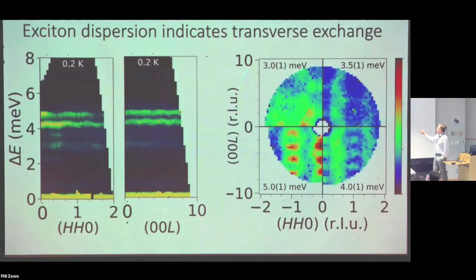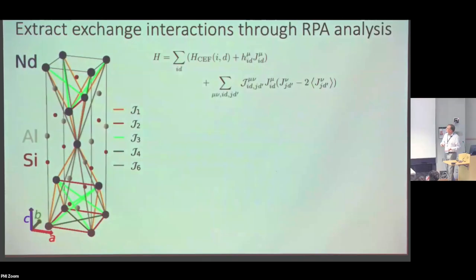This is another way of showing the same data, actually, which is just a slice through these same data at 3 millielectron volts, and you can see these things sort of coming into view and leaving view at different energies. So this is 3, 3.5, 4, and 5, sort of moving in this region, we get these interesting structures. So there's quite a lot of information in the data, and all of that we're going to try to use to determine the exchange constants.